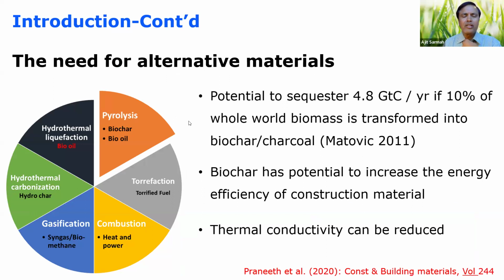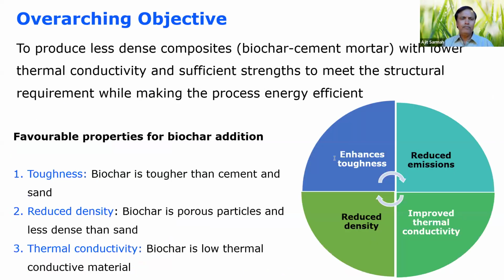Basically, when you pyrolyze, you can get biochar and bio-oil. With torrefaction, you can get torrefied wood, which we talked about. So there's a potential to sequester nearly 4.8 gigatons of carbon per year if 10% of the whole world's biomass is transformed into biochar and charcoal. Biochar also has the potential to increase the energy efficiency of construction material, because thermal conductivity can be reduced. If you can reduce thermal conductivity and the flammability of the material, then it is good, because even if a building catches fire, the damage may not be that much.